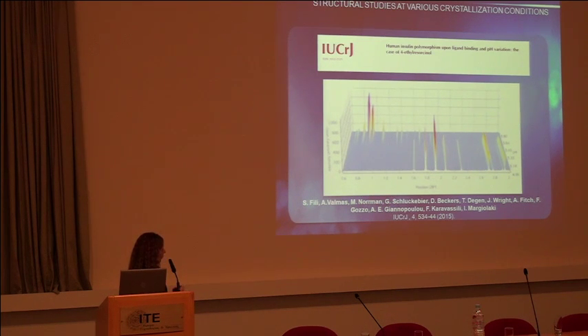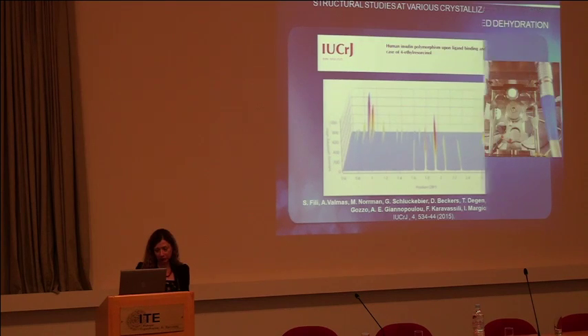So, first observation in a very quick experiment is that the positions of the diffraction lines change drastically at a certain crystallization pH, and therefore we knew immediately, in less than 1 hour, that we have a clear first-order phase transition upon pH variation. This is an example, but you might be interested to vary different parameters, such as the temperature or the concentration of an agent. So again, this was one example to prove the screening aspect of the method.